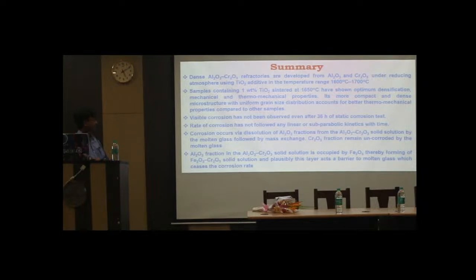And corrosion occurs by dissolution of the alumina fraction from the alumina chrome solid solution by the molten glass, followed by mass exchange. And the Cr2O3 fraction remains uncorroded by the molten glass. Cr2O3 is not participating in that. And the Al2O3 fraction in the alumina chrome solid solution is occupied by Fe2O3, and thereby a Fe2O3, Cr2O3 solid solution forms. And this layer acts as a barrier to the molten glass, which ceases the corrosion rate.